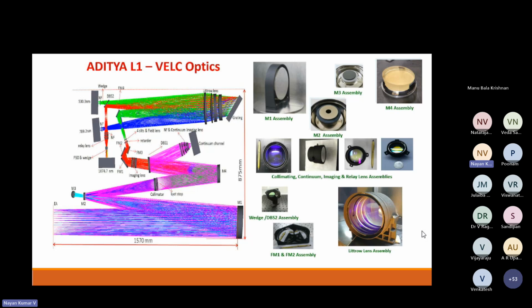And the challenge we faced in M1, we faced much more than that in this lens assembly. These are Japanese glasses we have used, and as per our mechanical design, initially we saw it should be able to withstand, but when we subjected it to the endurance test, it cracked and came off. So we had to revisit all this, and it took a lot of time for development, and then we could finally qualify it with a lot of reinforcements within the assembly for each lens, and then stacking them in that assembly. So a lot of things have been done. This is a technology which we are yet to publish, but it may come very soon.